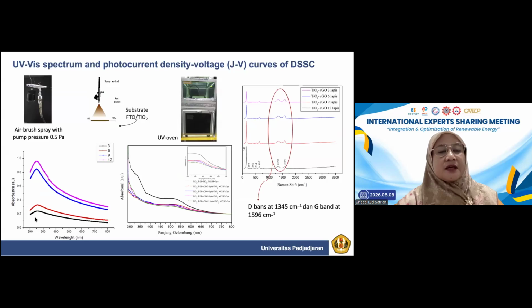So we can see here that this is the UV spectrum. By adding up to 12 layers of reduced graphene oxide, we can see that the absorption is increased. Increasing the absorption will also play an important role in improving the efficiency of the devices. We used Raman spectra to find out whether the reduced graphene oxide has been deposited successfully on top of the TiO2 photoanode. Here the Raman spectra show D bands and G bands, which are the bands for the reduced graphene oxide.